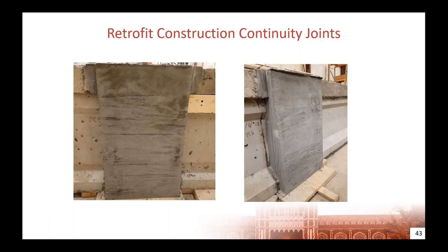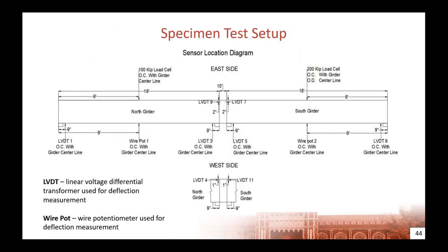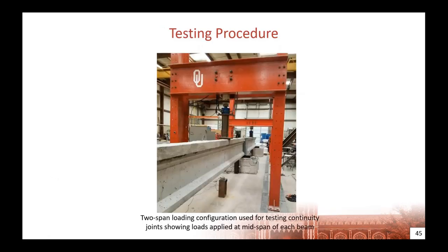And then for testing these specimens, we looked at two different tests for each girder specimen. It was a two girder, a single joint specimen, so a two span system. We would do one test for negative moment where we had supports at each end of the girders with the joint in between. We'd have a single point load at mid-span of each girder. We would measure deflection underneath the point load, measure deformation of our bearing pads with LVDTs at each point, and then measure any opening of the joint at the interface between the beam and the UHPC connection. We would also do a positive moment test where we would remove this center support and test with those same point loads to see what would happen in terms of positive moment resistance at the joint.